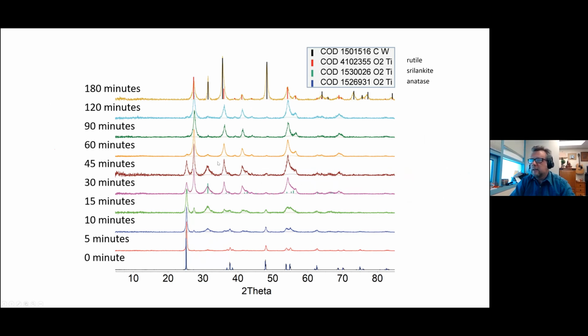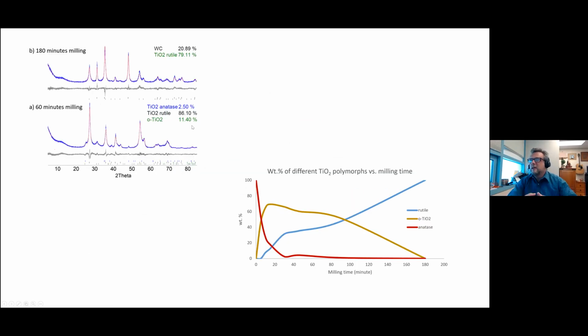And we observed that we first see signatures of the intermediate phase, srilankite, that increases with the duration of the grinding and then starts disappearing with the final phase, the rutile highest density phase, forming. We also noticed that if you grind for a long time at really high energy with tungsten carbide components, you grind off some of the tungsten carbide, which in some instances becomes a problem.